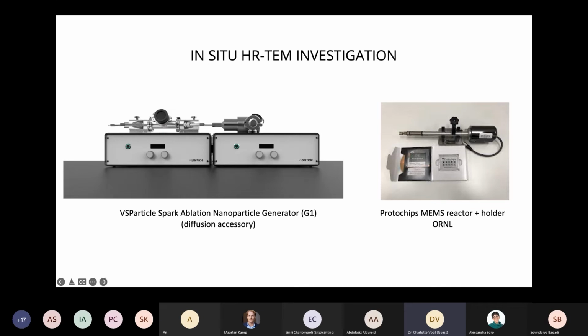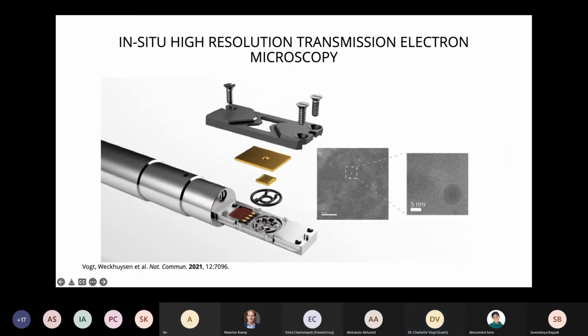Using diffusion means that you're going to get all of the different nanoparticle sizes within the aerosol that you create from sparking. So here we are. We loaded this silicon nitride membrane cell into our Protochips holder, and as you can see, we were able to take larger scale images. We saw that there were some larger nanoparticles, some smaller nanoparticles, and we can really zoom in onto whichever particle size we wanted.